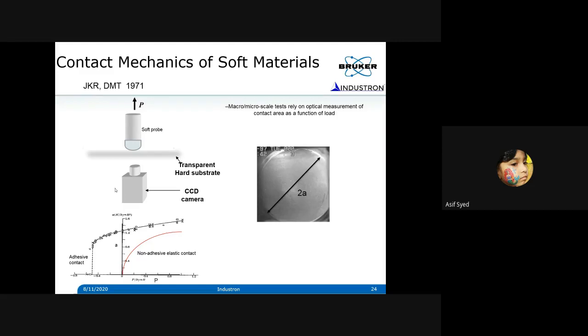where they used a very simple setup. You take a probe, a big probe, millimeters in size, and a transparent flat substrate, and then you put a camera underneath with an optical microscope so that you can see the probe from underneath, because this is a transparent substrate. You can see underneath as you make contact, and then you slowly pull it out. You can measure the force through some kind of strain gauge load cell as you pull this probe out. At the same time, you can see all that contact in the optical microscope, and you can record how the contact is changing as you pull off.